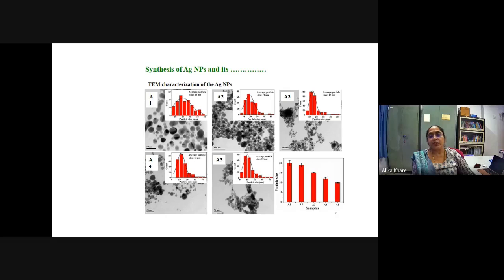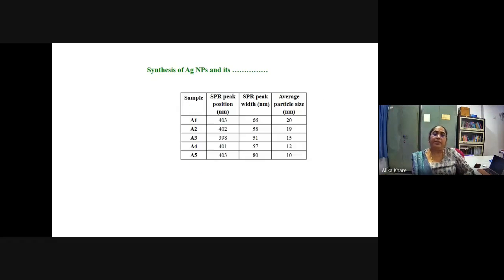With exposure time it is changing, and with increase in laser energy it is also changing. What happens is that when we increase the exposure, the particles formed with the previous shot of the laser get broken up with repeated shots of the laser, so the size changes. With increase in energy, liquid droplets are formed, and with repeated impingement of the laser, the droplet size keeps reducing, and we get smaller particle size.